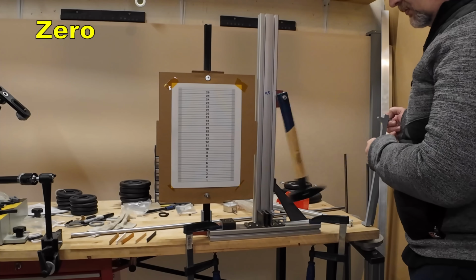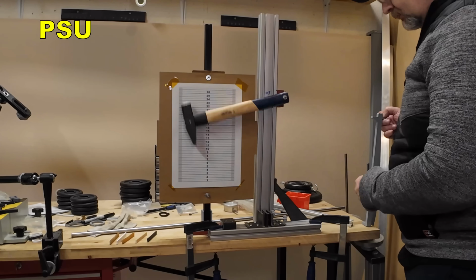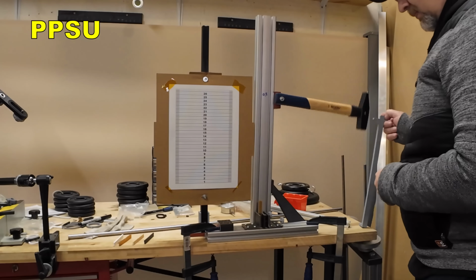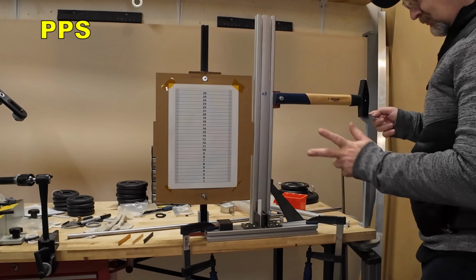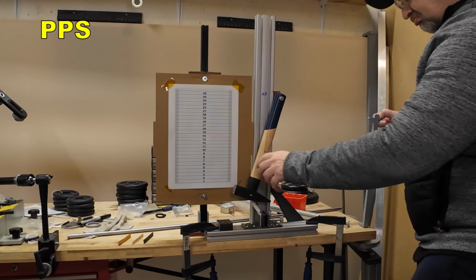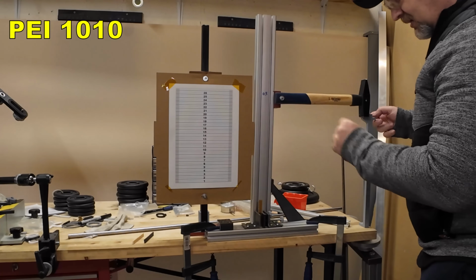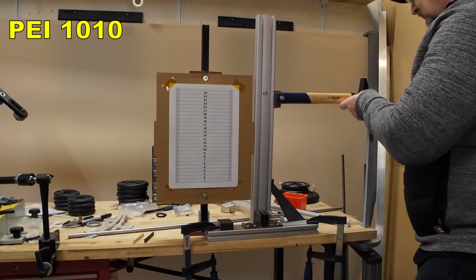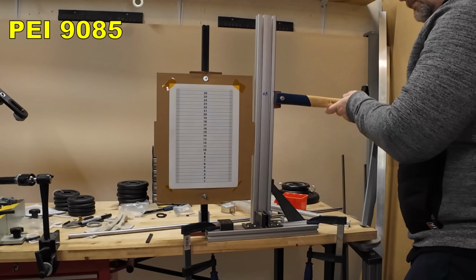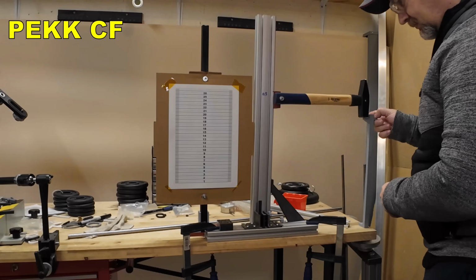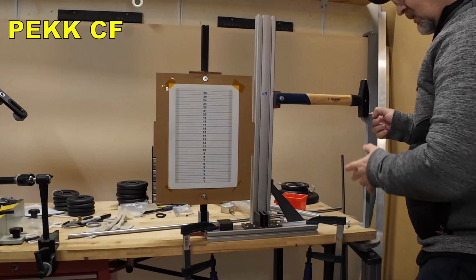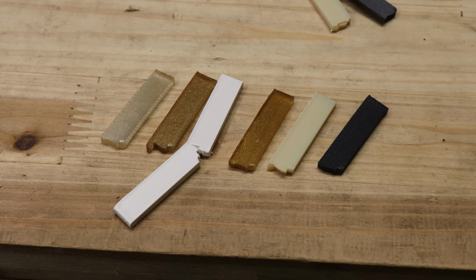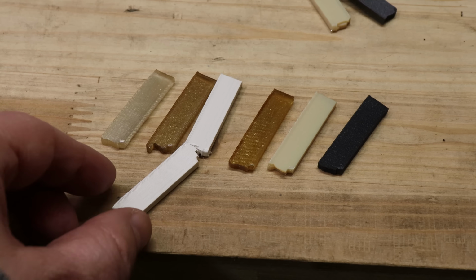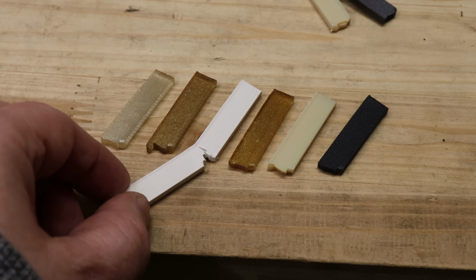Impact test, the zero position, PSU, PPSU, PPS, PEI 1010, PEI 9085, and PEKK-CF. More or less these are brittle materials, of course not like PLA or PETG, but the toughest from these is the PPS, but again I can see some correlation between weaker layer adhesion and resistance to impacts.